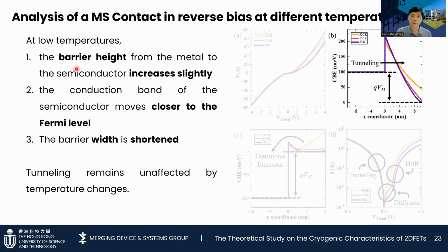At low temperatures, the barrier height from the metal to semiconductor increases slightly, while the conduction band of the semiconductor moves closer to the Fermi level. Figures on the right-hand side also illustrate that the carrier conduction under the reverse bias is mainly due to tunneling and remains unaffected by the temperature change. Also, the increased barrier height is offset by the narrowing of the tunneling barrier, which cancels the effects of each other. Therefore, we can say that the reverse current remains unaffected by the temperature.